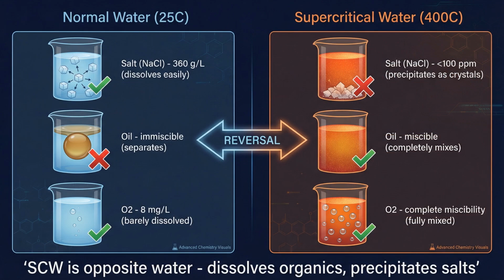This property change creates remarkable opposite behavior. Normal water dissolves salts readily. Sodium chloride, for example, reaches 360 grams per liter. But supercritical water can dissolve less than 100 parts per million of the same salt. It simply precipitates out. Meanwhile, organic compounds that are practically insoluble in normal water become completely miscible with supercritical water.